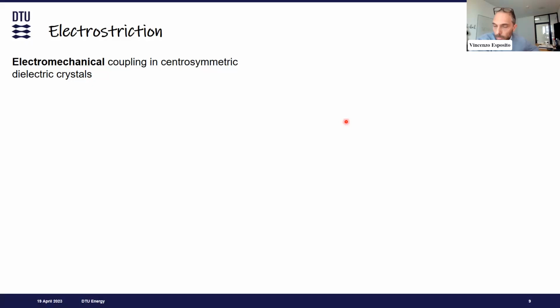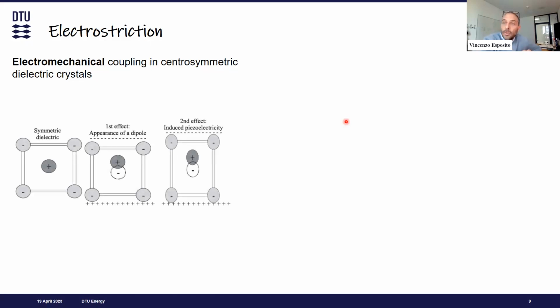So if we want to go back to our defective metal oxides as electromechanical functional materials, we will see that they have a response which is typical of electrostrictors. And here I want to open a very tiny parenthesis on what electrostriction is. Electrostriction is a common phenomenon for all insulating materials that, under an electric field, give a separation of charges. This separation, of course, leads to actuation, or change of shape, or strain in the lattice. So we have here already a difference between electrostriction in centrosymmetric materials and in piezoelectrics. In this case, it is just actuation. We give an electrical signal, and what we get out of the material is a strain.